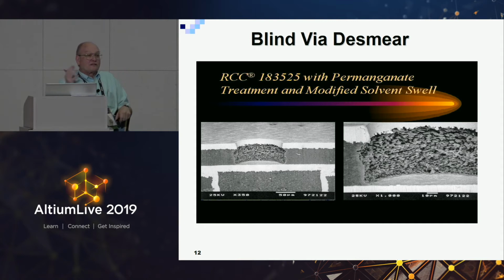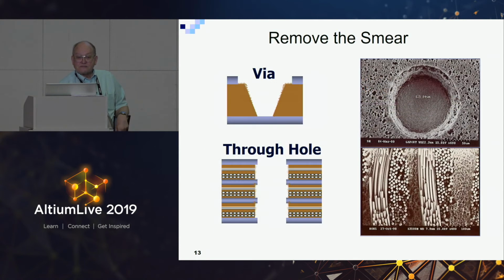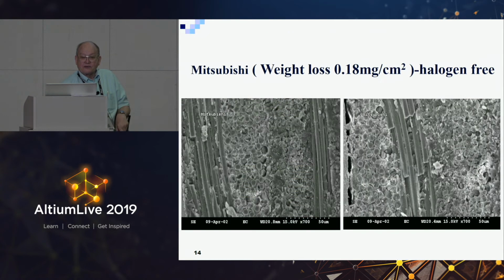Well, that is going to fail in the field. It's going to pass assembly tests, but not reliability testing. So this whole thing about removing the smear applies not just on a through hole, but on the blind via, especially at the very bottom down here. That's a very critical area that's tough to get to. One of the things that was interesting was the improvement in halogen-free material over the traditional FR4. As the Japanese especially started demanding halogen-free laminate, the laminate got re-engineered under modern times, and although slightly more expensive, it was slightly better than the conventional FR4 that had halogens in it. So we've seen a trend towards improvement in performance with halogen-free materials.